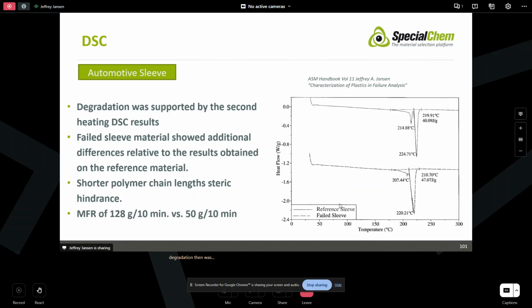Degradation then was supported by the second heating run. The failed sleeve showed additional differences relative to the reference. We're seeing that PBT in many cases, this is our reference, exhibits this kind of bimodal melting endotherm on the second heating. You see that that's not really present there. Again, our melting point is almost 5 degrees lower. We supported that by melt flow rate, and again, that supported our conclusion that we had undergone molecular degradation.